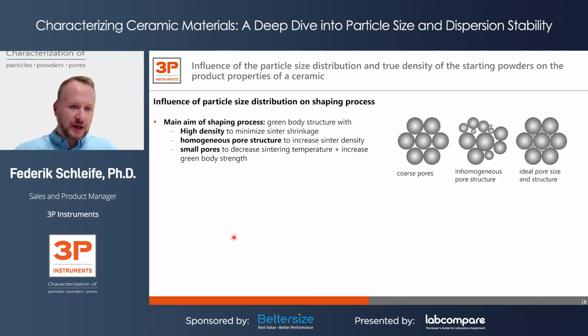So first of all, let's talk about the influence of the particle size distribution on the shaping process itself, so during the formation of the green body. What is the main aim of the shaping process? The main aim is that the green body structure comes with a high density, comes with a homogeneous pore structure, and comes with small pore sizes.